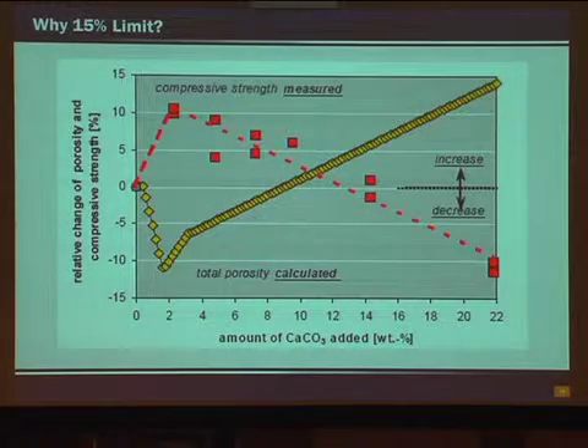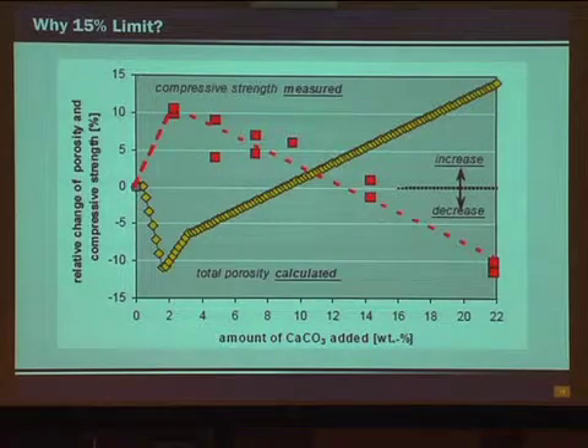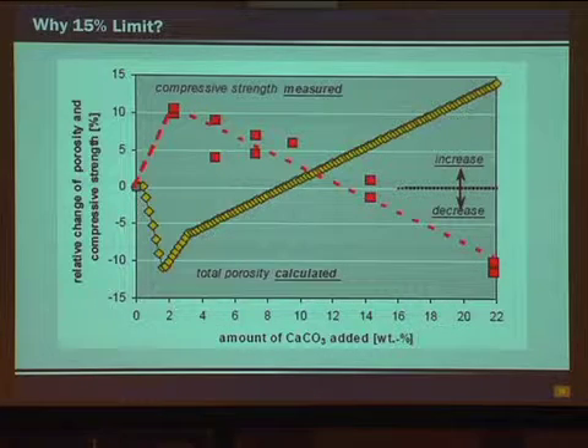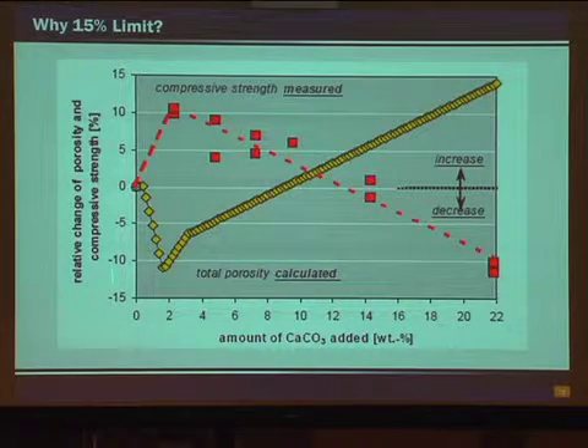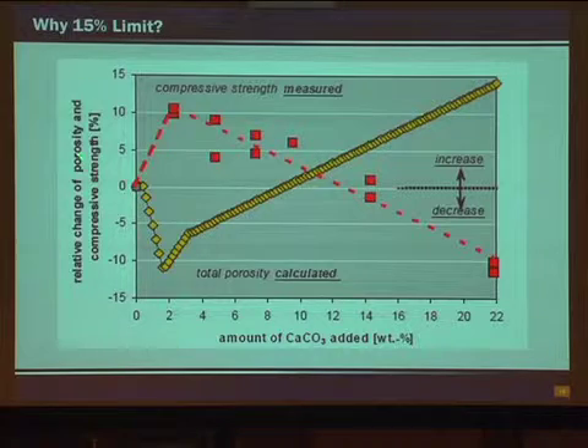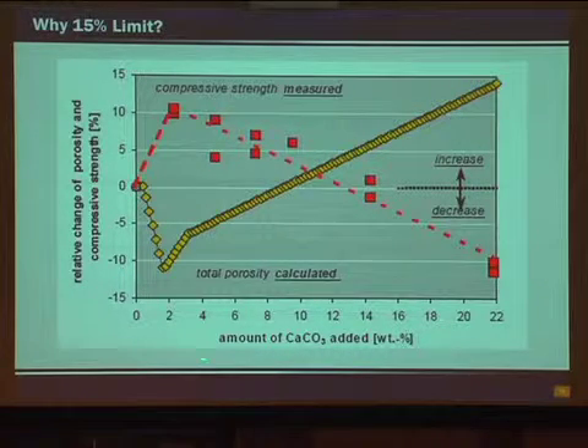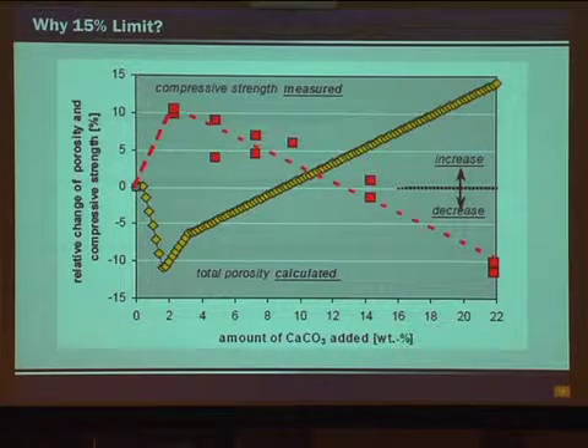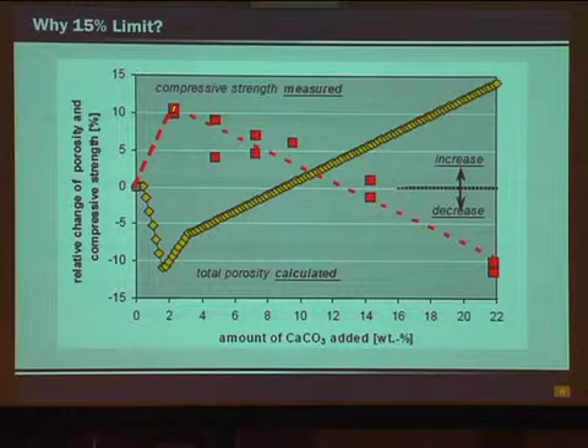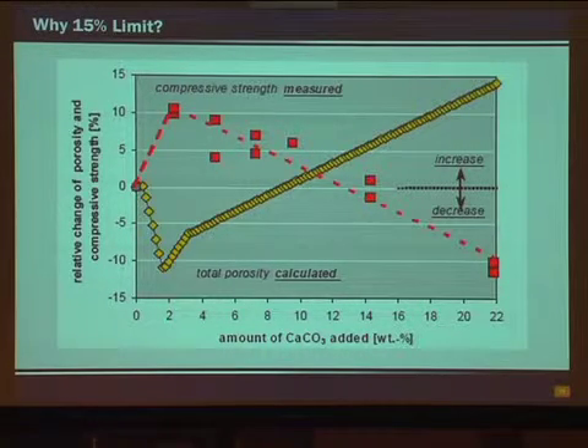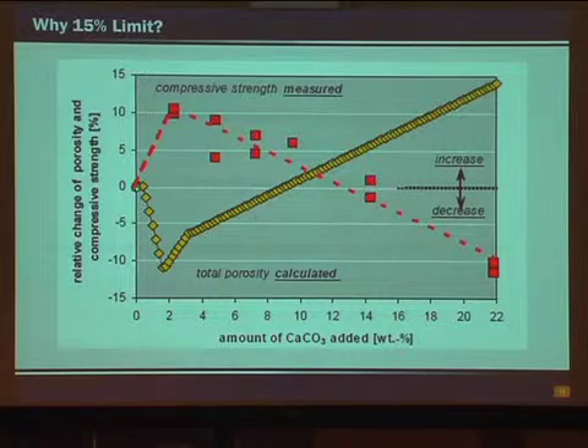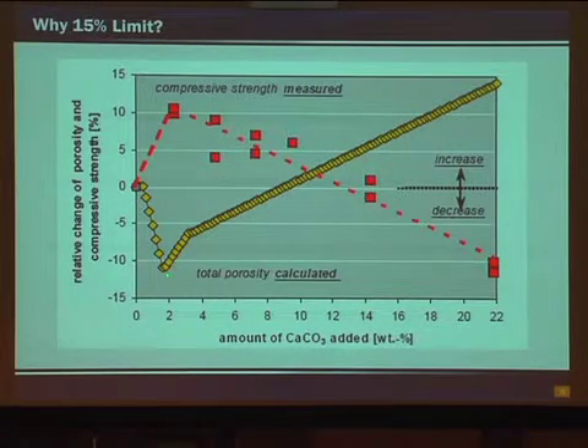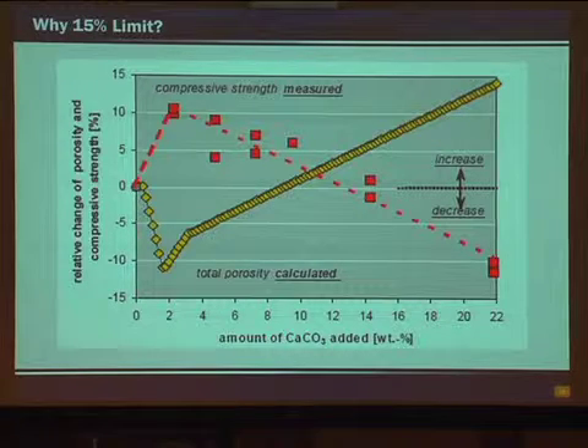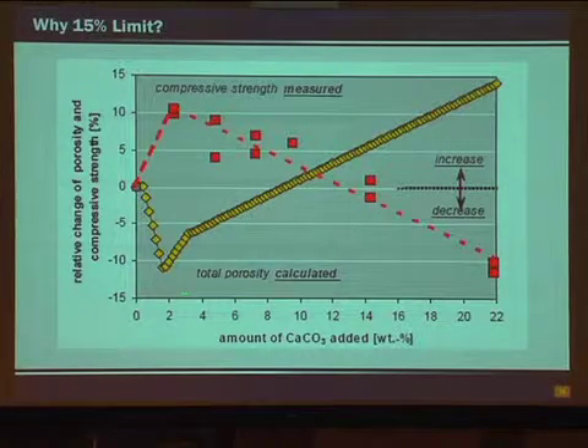All right, this is explaining why we set a limit of 15% limestone addition. So on this side of the chart, we have relative change of porosity and compressive strength. And this is limestone addition here. So if we add about 2% limestone, we have this fairly significant increase in strength and a decrease in porosity, which makes sense, right? Strength is related to porosity, so as porosity goes down, strength should go up.